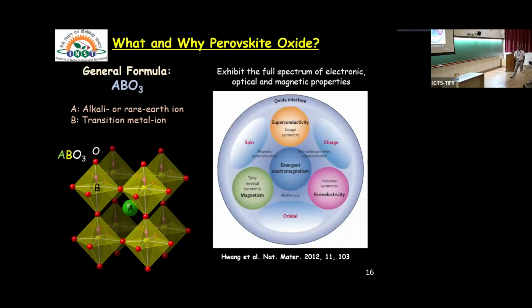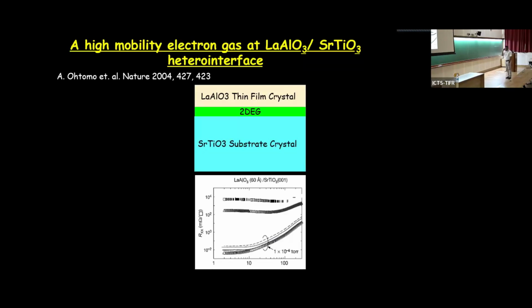Why is this kind of perovskite material interesting? If you think of any interesting physical property, superconductivity, magnetism, ferroelectricity, and so on, and the connection between them, that is the coexistence of them, you can find it in this kind of material. So the first story of the conducting interface of this perovskite oxide started with the lanthanum aluminate and strontium titanate heterostructure, where both are high bandgap materials, but the interface becomes conducting when you juxtapose one on top of the other. And this is the resistivity data as a function of temperature. It goes down with decreasing temperature. This is work done by Ohtomo and Hwang.